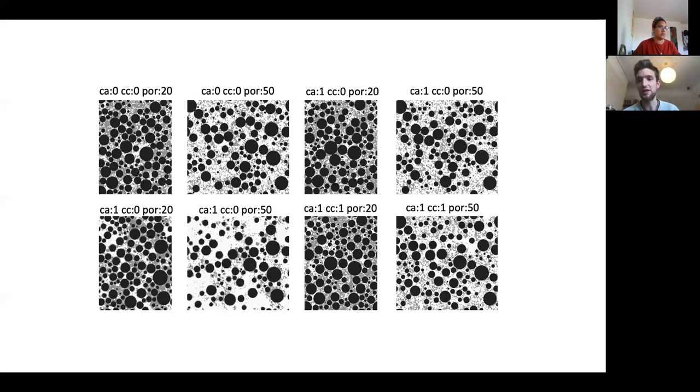even if we find that the optimum is on the edge of some parameter, we can take it, we can train a new GAN where we explore off into that direction. So if we have 20 and 50% porosity that we're trained on, we find 20% as optimum, make a new image with lower percent porosity, try it again, and that will be a legitimate stage of that process.